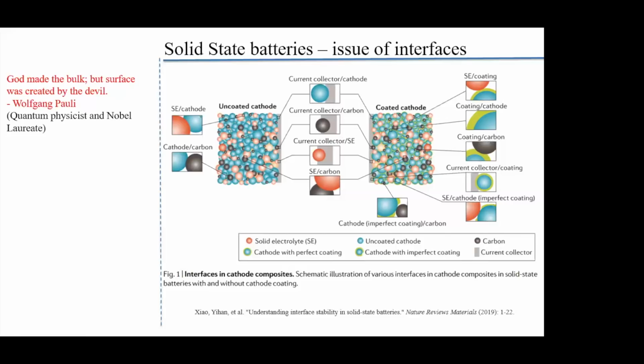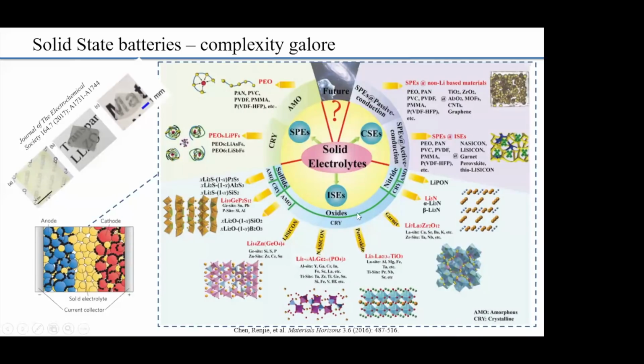And then there's the issue that some of these oxides are pretty stiff and brittle, right? So if it is very brittle, how are you going to make a cylindrical cell? Or maybe you just need to make a flat pouch cell, and make sure there is no inadvertent pressure on these kinds of batteries. If the battery is a little bit compliant mechanically, that's good, because it gives it a kind of toughness. But if it is too brittle, that can become a failure point on its own, because one brittle fracture can lead to an isolated region, which could lead to all kinds of problems.